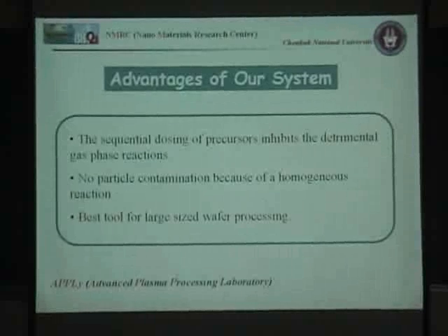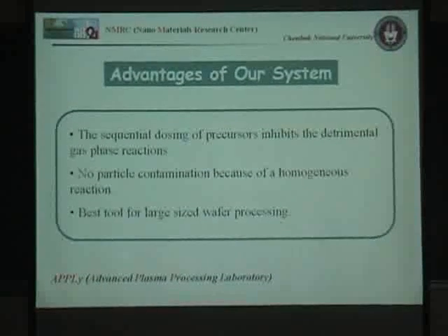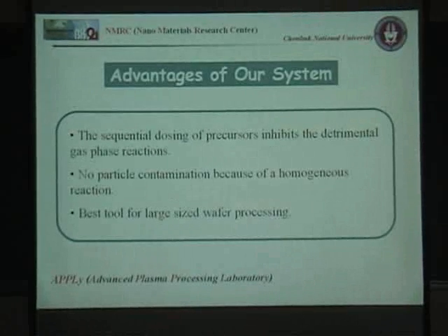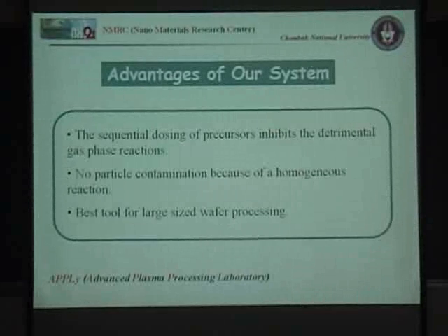Now I come to the advantages of our system. The system we employ for the fabrication of these flower-shaped and needle-shaped zinc oxide nanostructures is a variant of chemical vapor deposition. Our system is based on sequential, complementary, self-limiting and saturated chemical reactions. Each precursor is introduced into the reactor chamber after a certain time interval. Due to these mechanisms,